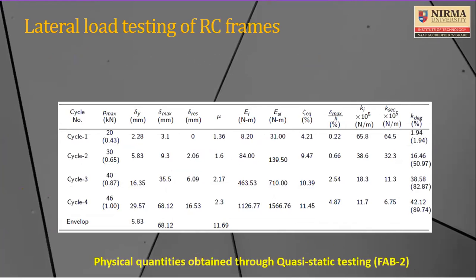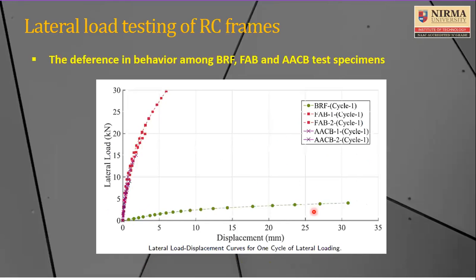So you can see that the original damping ratio is almost 3 to 4%, but with the damage it progresses up to 11% or 12%, which we never consider in our analysis. And this plot is very important, which we have compared only for the first cycle. From this, you can understand that a bare frame has a very low lateral load carrying capacity. But as you can see, the fly ash and AAC block both have a very good capacity to resist the lateral load.